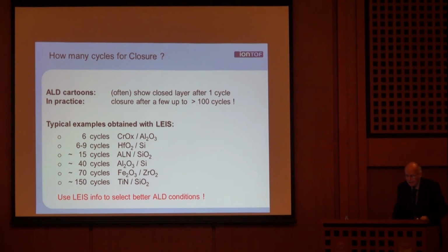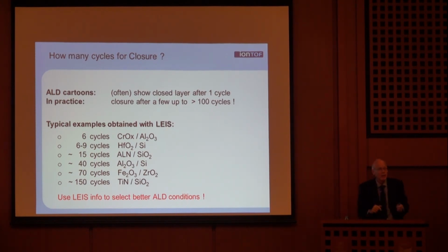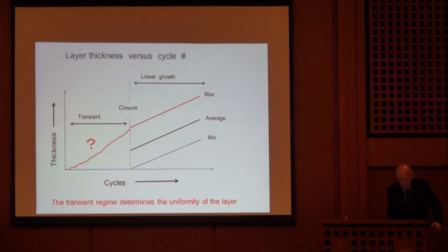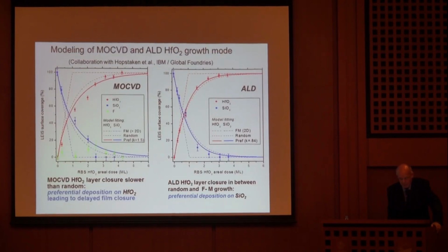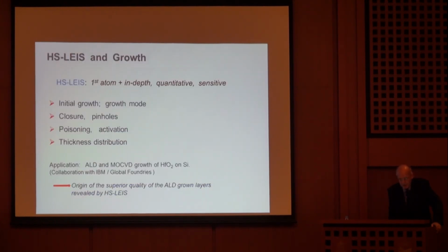And depending on how good your chemistry is, you do it in cycles. If you are very lucky, in a few cycles you can get closure. Very often you need many cycles, which means I have big mountains and there are still pinholes at the same time. And so that is not good. Let me see. So this is an example with IBM where we got better.